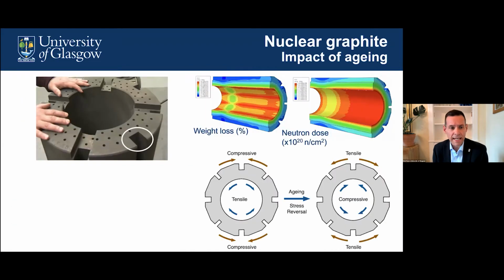If you look a little bit more closely at a typical graphite brick, you can see it's quite a strange geometry. During the many years of operation, subject to radiation damage, there's significant weight loss, loss of strength, loss of stiffness. Early in life, the individual bricks are subjected to a complex stress state where the outside is in compression and the inside is in tension. But due to aging, at some point during their life, there's a stress reversal process such that the outside of the graphite bricks becomes tensile.